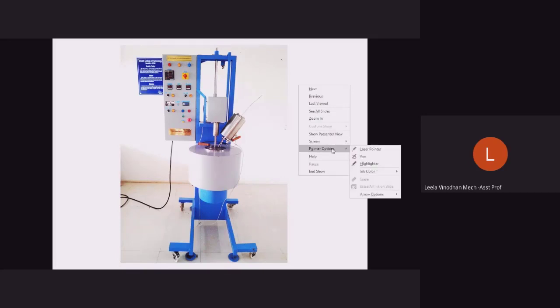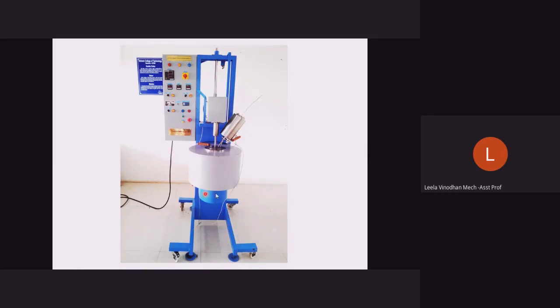This is the furnace where you have a limited volume of crucible. Basically, it is SS304. Otherwise, you can use another material also, 310S. It depends on the temperature, how much maximum temperature we are going to reach. If you are going to limit to 700 or 750 degrees Celsius, then SS is more than enough. The SS crucible may have a volume of 1.5 kg or 2 kg. The furnace size is basically based on how much volume we are going to take inside the crucible.